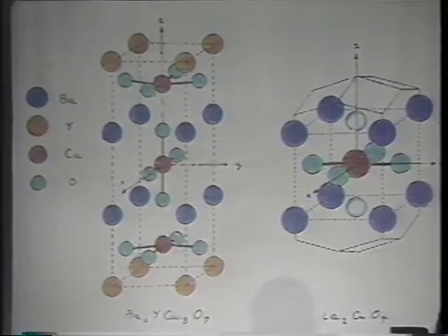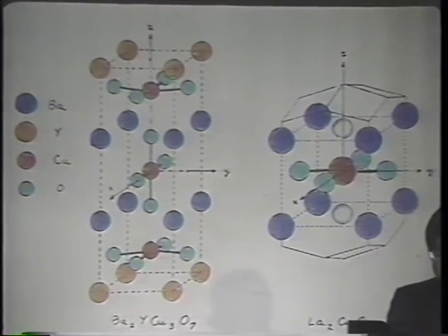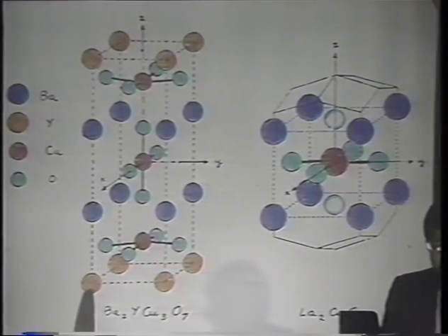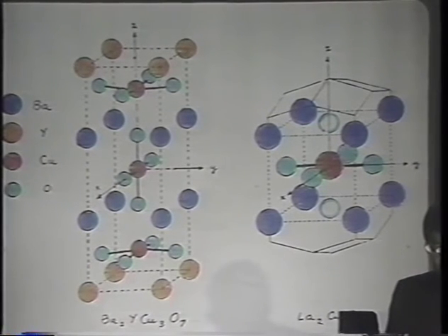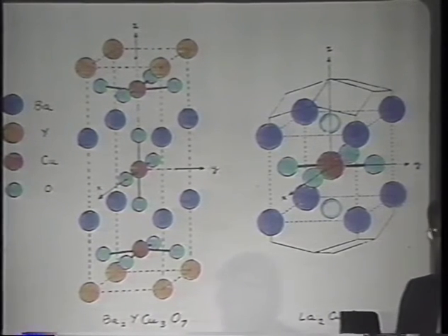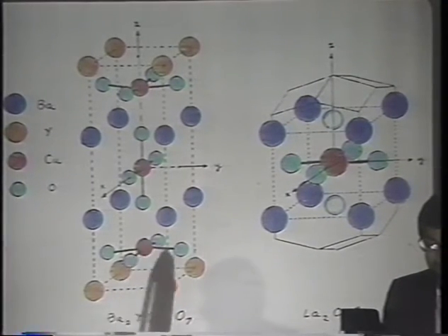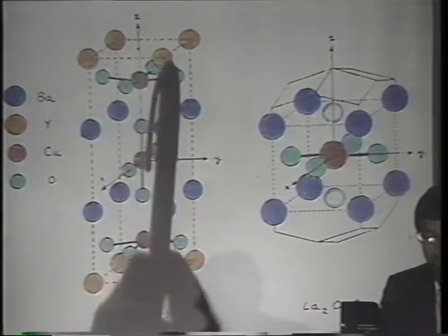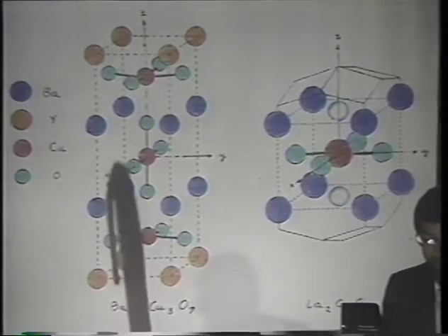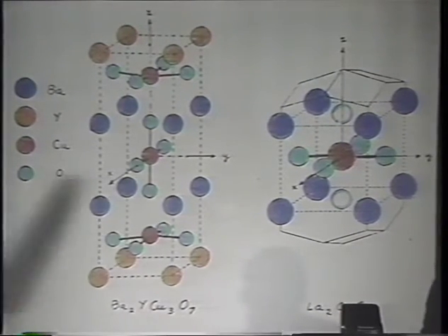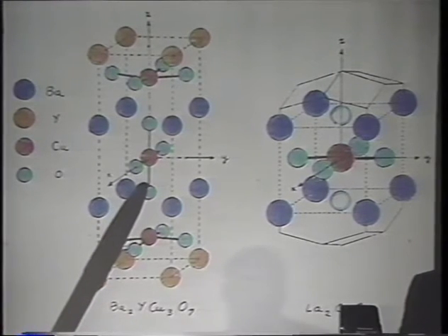Now, in the 90-degree material, the skeleton of the donor atoms, I may call them, is surprisingly isotropic. It is a cubic perovskite phase, or almost cubic. However, this is misleading. The conducting pieces, again, are planes, as shown here, between the yttrium and the barium planes. And then, to a big surprise, a new element comes in, and this is the structural data of the Bell Labs group, a new element which is a one-dimensional chain.